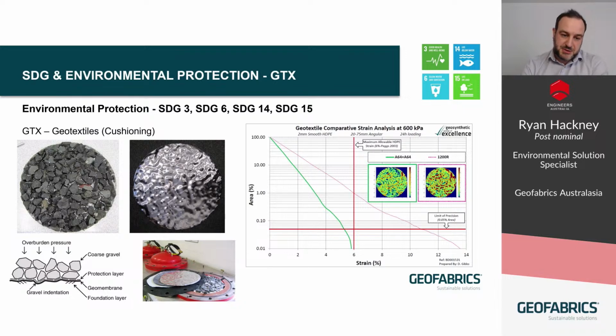So we can measure this in the laboratory by setting up this system in the lab, by taking a drainage aggregate material and then placing that on a geomembrane with the cushion geotextile sitting between the two, as it would on site. And then within that system, we have what we call an aluminium recording plate. You can see a picture of that in the middle. We impose the load that this system is going to be subjected to on site. And after a 24-hour period, we can then remove that aluminium sheet, which records those indentations of that aggregate under load. We can laser scan the aluminium sheet, which measures deformations every square millimeter. And then from that, we can calculate the maximum strain that's being imposed on that membrane.